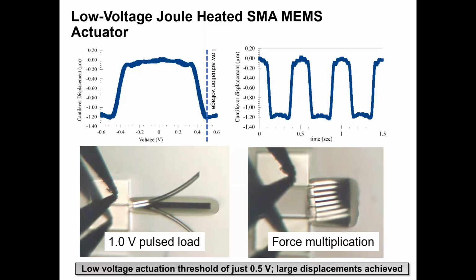So what I was saying is that these curves were experimentally generated using laser Doppler vibrometry, where a laser beam spot was focused onto the beam to monitor deflection over a range of applied voltages at low frequencies. The shape memory effect was characterized by the large downward slope, which starts at about 0.3 volts and is fully actuated at half a volt. There's a symmetry about 0 volts because the sweep went from positive and negative voltages at a slow rate of 2 hertz. The linear regions before and after the actuation are most likely due to the CTE mismatch between NiTi and SU8. The magnitude of deflection is significantly more pronounced and over a very tight voltage interval, indicating that the Joule heating did induce a shape memory effect, which was sufficient to cause large and reversible two-way shape memory effects at low voltages.